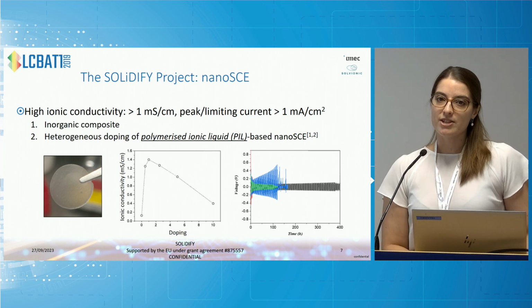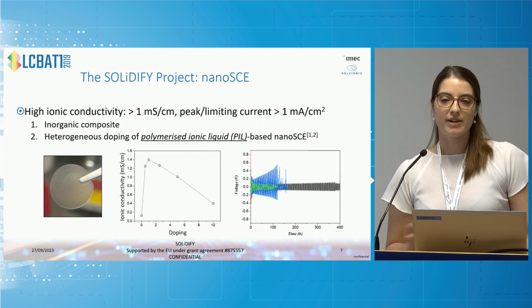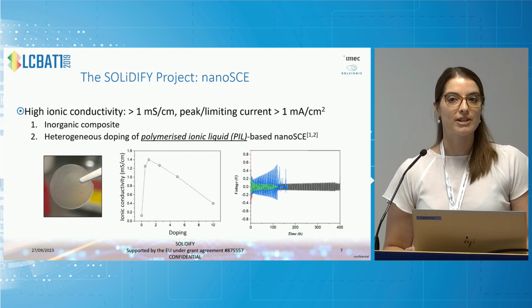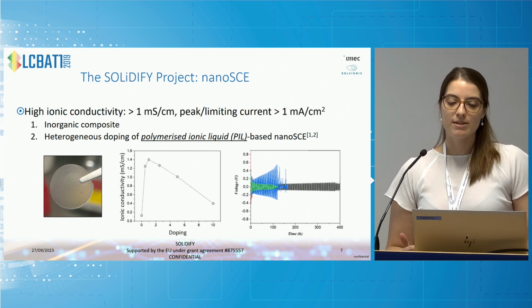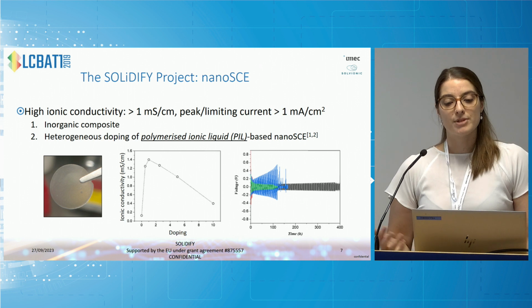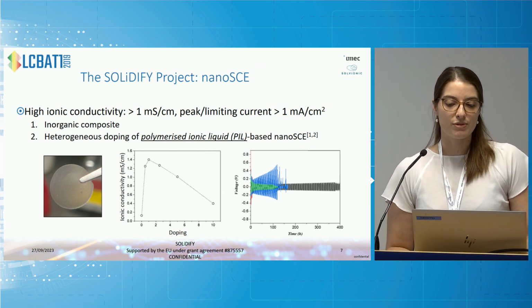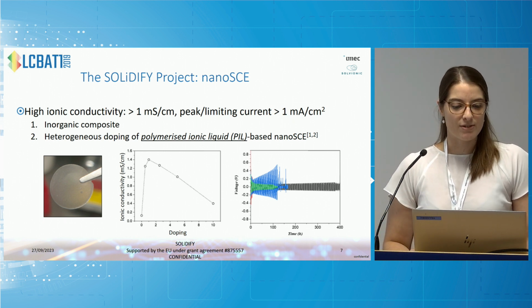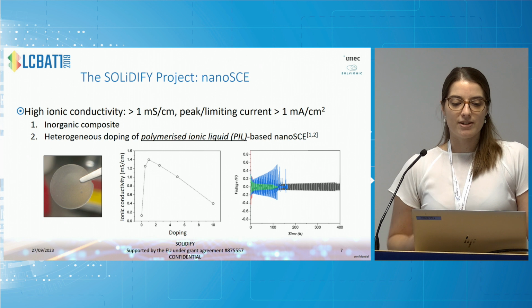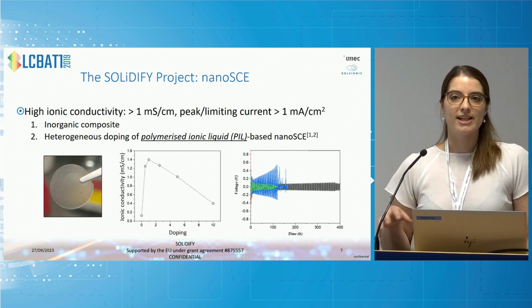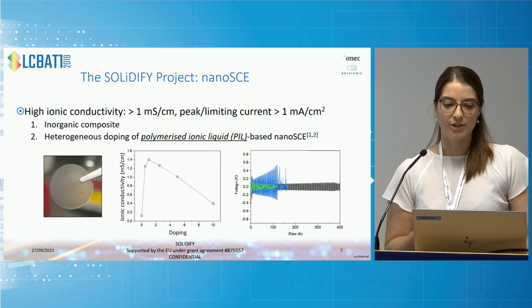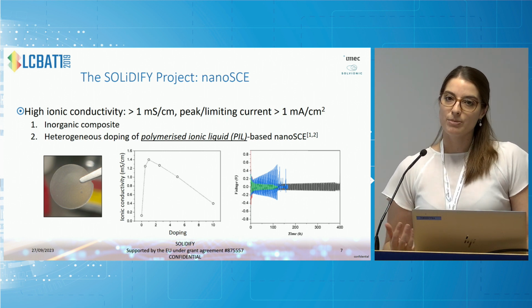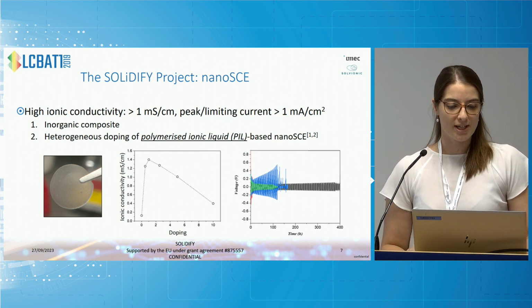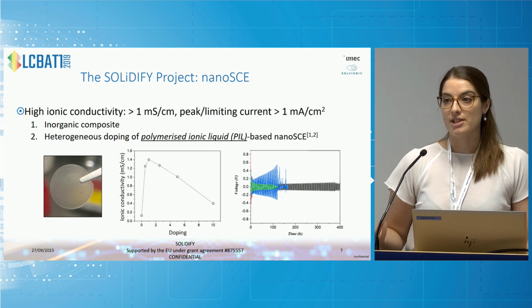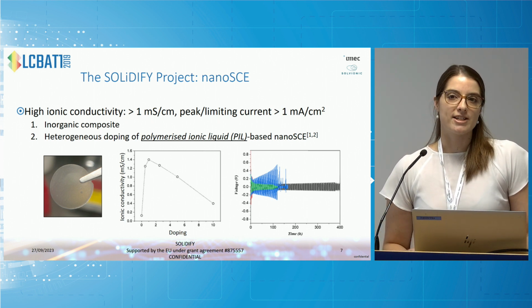So delving in further to each constituent component, we've developed high ionic conductivity nano-solid composite electrolytes, so more than 1 millisiemens per centimeter, with peak limiting current so far more than 1 milliamp per square centimeter. These are quite important aspects, of course, of the electrolyte, as we all know. And there are two, let's say, veins that have been investigated within the SOLIDIFY project with regards to the electrolyte. There's an inorganic-based nano-solid composite electrolyte, and there's also this heterogeneous doping of a polymerized ionic liquid.